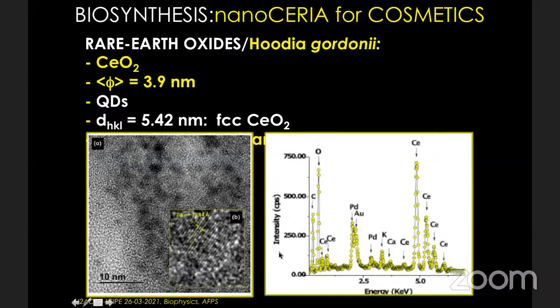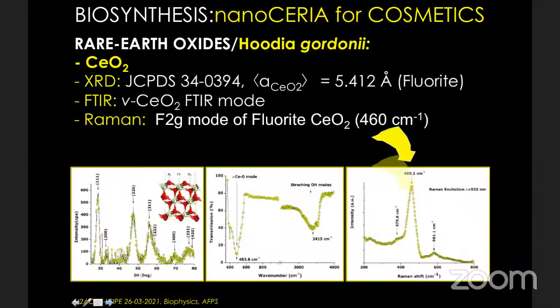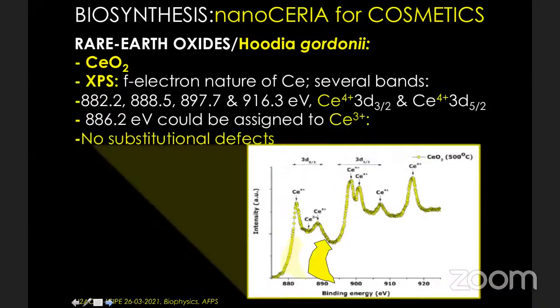They are quantum dots. And when you check the purity, you will find some calcium and some potassium from the natural extract, but they can be removed easily. The palladium and gold come from the coating itself, because we also want to see how much carbon is inside. And when you do the study of surface and interface characterization, you will find the signature of XRD of a pure fluorite. With FTIR and Raman, you find that it's high quality. And with XPS, you will find that the cerium is only in the 4+ valence. It's a pure cerium oxide, CeO2, with a minimum of defects.